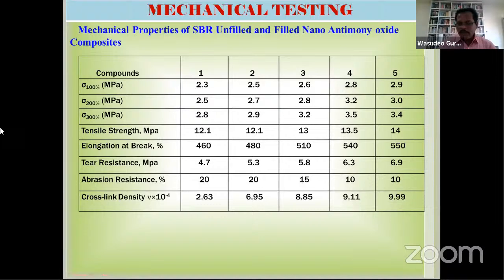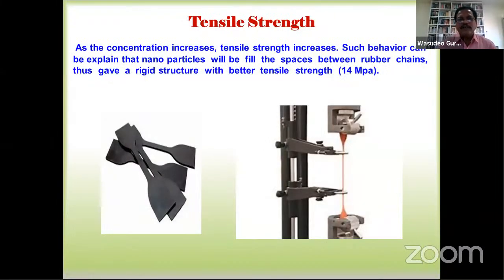Now here, this is the tensile strength, and when we measure the tensile strength, first of all we have to cut the rubber sheet in a dumbbell shape in this way, and then here this is the instrument to measure the tensile strength. Now we have to put this sheet here, and we can also measure elongation, also we can measure the strength. As the concentration increases, it is observed that tensile strength also increases. We can explain this behavior by the introduction of nanofiller particles in the rubber chain or rubber matrix. They form a rigid structure, and therefore they give a good tensile strength.